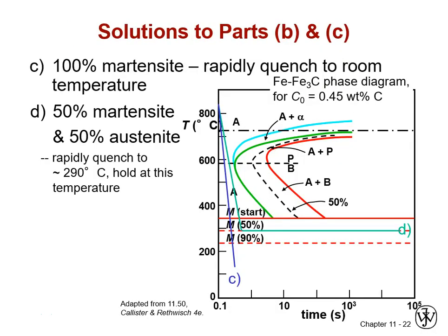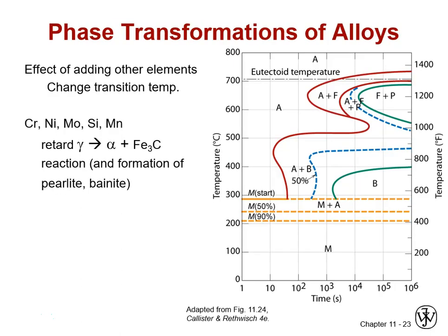Whereas if we look at the slide before, we were starting to get alpha ferrite and bainite forming at less than 1 second. So obviously, if we can quench from austenite temperatures down below 500 or 450 in 10 seconds, we can form 100% martensite. So especially if we have a thin part, that's very doable.